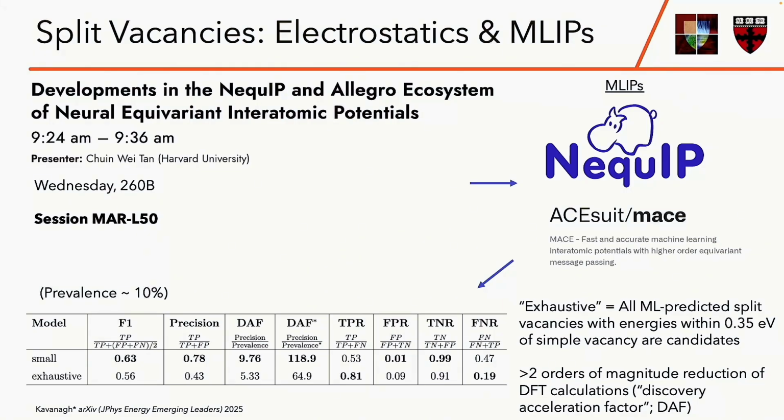So just one other point to mention here is that I've trialed both the MACE and the NequIP interatomic potentials for this task, which thus far have achieved similar accuracies, but with the NequIP model being around twice as fast due to some recent infrastructural developments, which my colleague Chun Wei will be discussing in his talk on Wednesday.